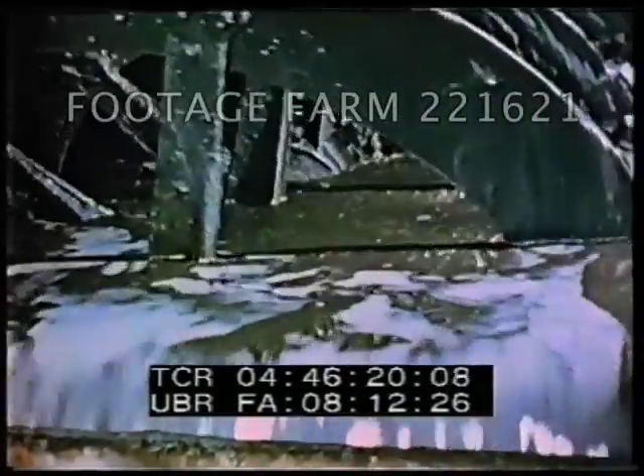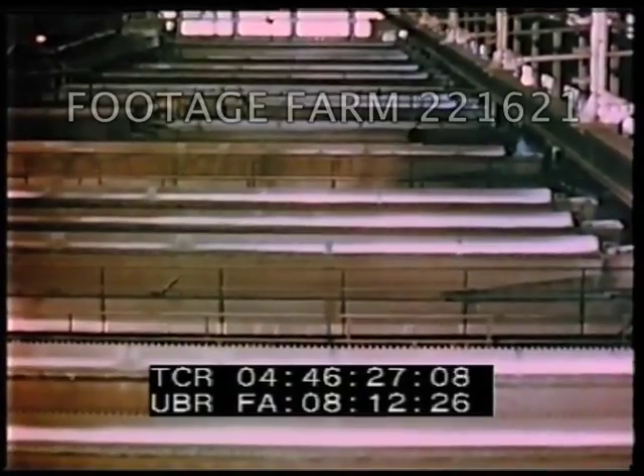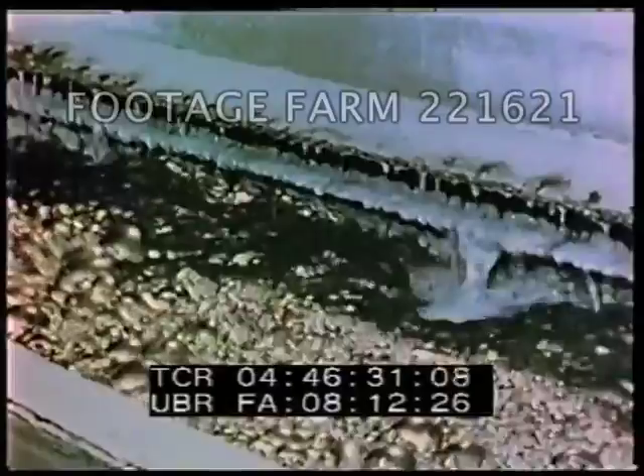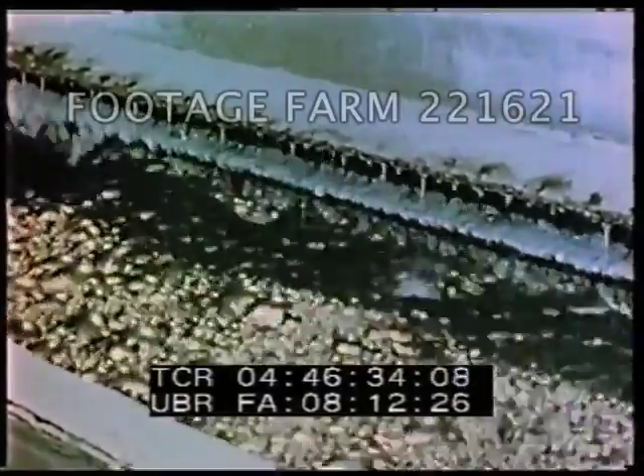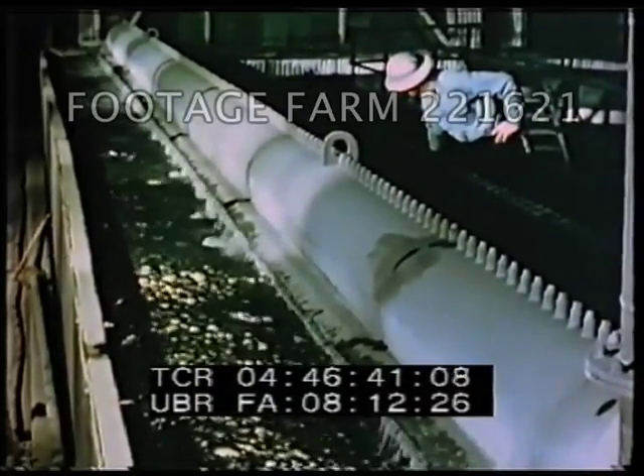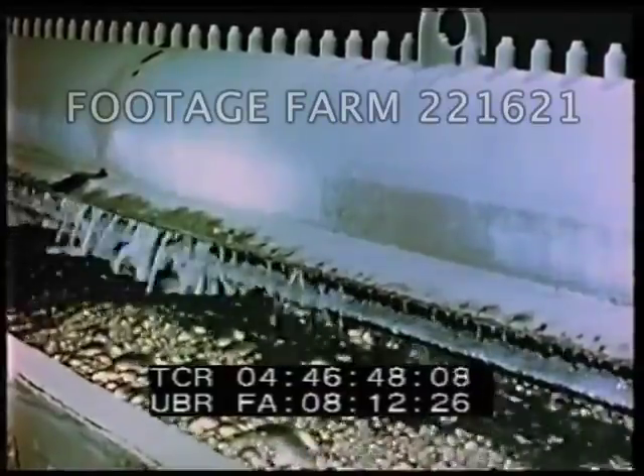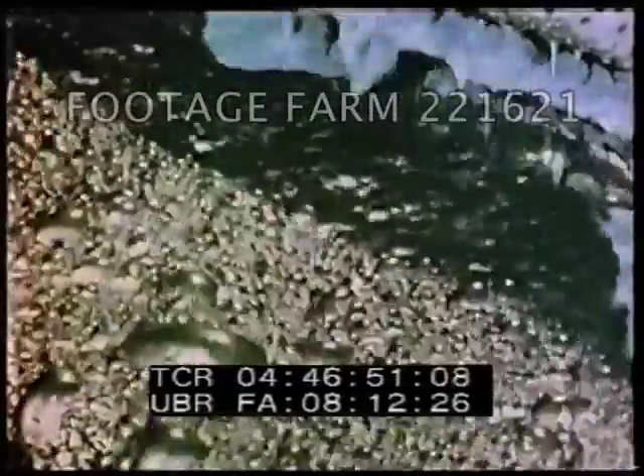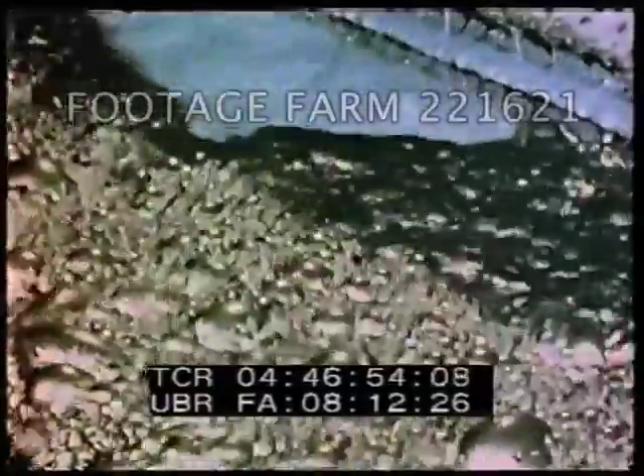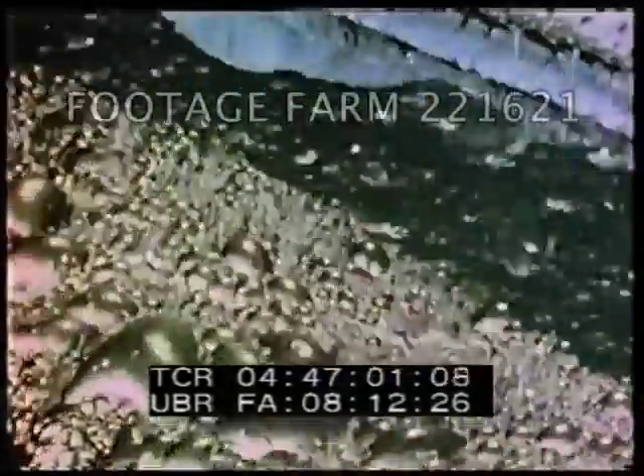The finished material overflows the classifier tank and passes to the flotation machines at a lower level. In these flotation tanks, called cells, the mixture of ground ore, water, and flotation chemicals is subjected to agitation by the injection of air, forming a mass of bubbly froth. The particles of copper iron sulfide — the chemical form in which copper appears in this ore — have been made water repellent by the chemicals added during grinding, and therefore have an affinity for the air bubbles of the froth. The froth collects them and carries them to the surface of the cells, leaving most of the waste material behind.